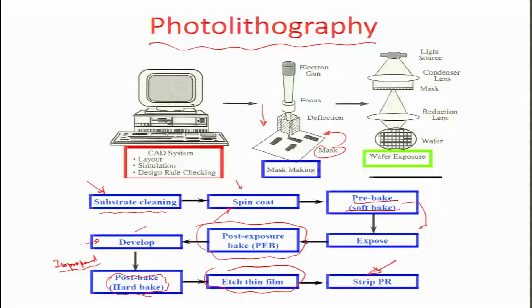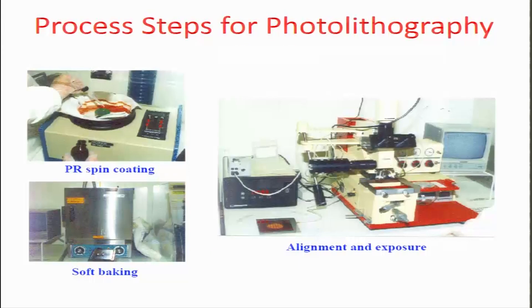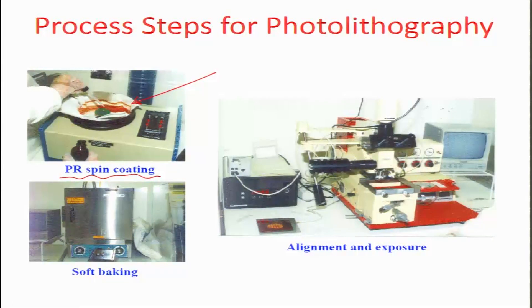Looking at the various aspects of the lithography process: it starts with spin coating of resist to spread it. There are typically three different components in a resist — a photo acid generator, an epoxy resin which cross-links on exposure due to photons, and a carrier solvent used for spreading the photoresist uniformly as a film on the surface. You drop the photoresist on the center of the spin coater and it spreads out as the silicon wafer rotates at a certain RPM. Then you do soft baking in a gravity convection oven.